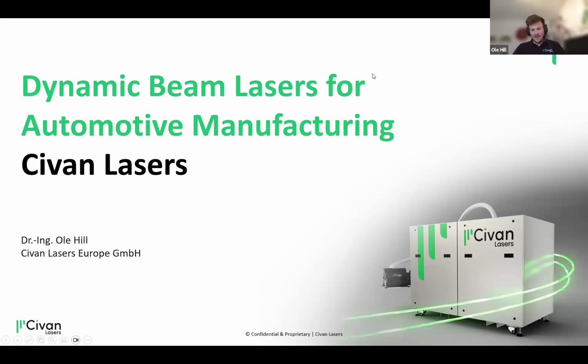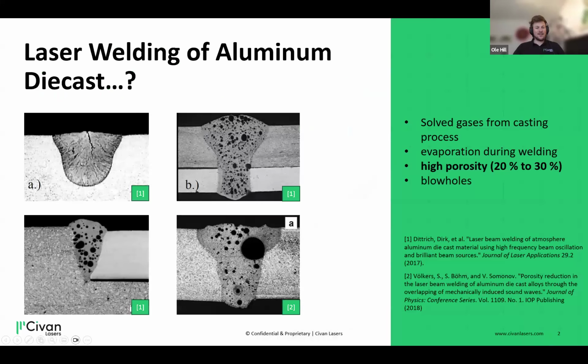So yeah, let's go to the first slide. So here you see a few cross sections of aluminum die cast welding that was done previously by research groups or some other manufacturers of unknown origin. And what you see in die cast welding is typically a lot of porosity. And it's such a strong porosity that the weld is not leak tight and also doesn't have a lot of strength because the pores can get so big that the interface is getting too small.